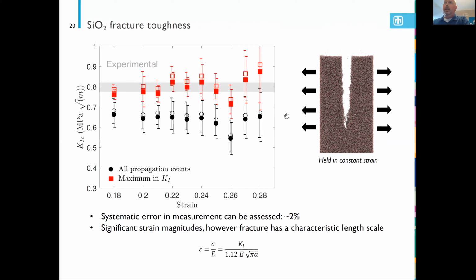And it's nice to see that our results nicely bracket this experimental result. But most importantly, the fact that the modeling result is somewhat consistent within error bars, and that the outlier at 0.26 strain is consistent over time, is important, because fracture toughness is an intrinsic property of the material. So I shouldn't anticipate any sort of strain dependence on the result. And so we're seeing somewhat consistent results.